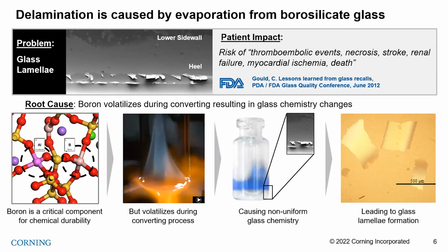And what's happening here is the volatilization of boron and sodium during this tube to vial converting process leads to changes in glass surface chemistry. So that blue coloration is actually a stain that we did to the vial surface, showing how non-uniform that boron can be after that converting process. And it's that region where it's been incorporated that generates flakes. And those flakes are rather large. You can see hundreds of microns, and they're very thin. So only a few microns, or in some cases less than a micron thick. So they are able to be drawn up into a needle and dosed as part of a pharmaceutical product. But of course, that's undesirable because it can have human health effects. Next slide, please.